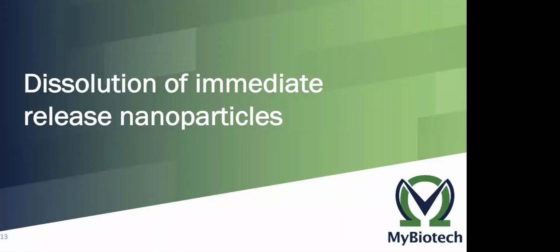And we have done some studies on the dissolution of immediate release nanoparticles. Especially in this case, the dissolution method is very important because immediate release tablets or immediate release formulations dissolve within 15, 30 or maximum 45 minutes. And when you do the same thing with nanoparticles, it happens even quicker. So you need a very efficient method to separate nanoparticles very quickly so that the dissolution process stops and you would be able to determine your real dissolution curve.